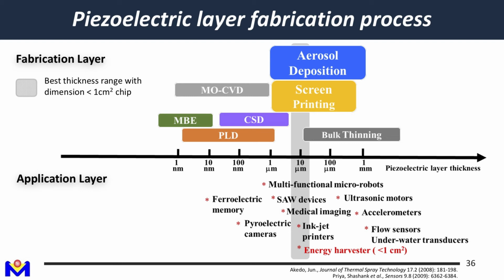And for thick film, around 10 micron, we have two processes in my lab. Screen printing is actually already quite mature. It can grow film around 20 to 50 micron. And also aerosol deposition. This is the dedicated method we adopt in our lab, originally invented by a Japanese researcher about 20 years ago.